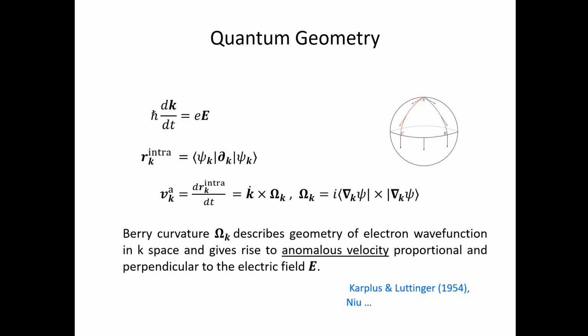This effect was first described in the classic work of Karplus and Luttinger, but it's only in the 1990s that the work of Qian Niu and others made a connection to this quantum geometry. So there's a simple way to visualize this effect. You can think of an electron wave packet in a solid as having a self-rotation around its own center. In addition to moving with a center of mass velocity and a well-defined position, the electron is also generally self-rotating around its own center of mass in materials that break inversion symmetry, or in materials that break time-reversal symmetry.